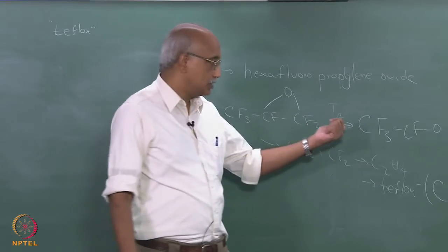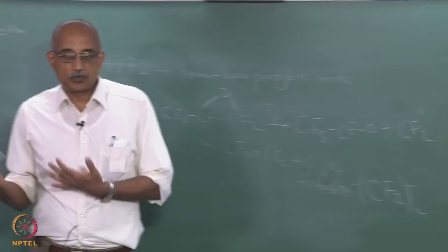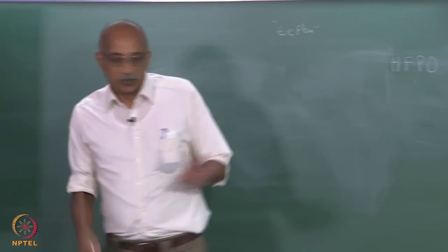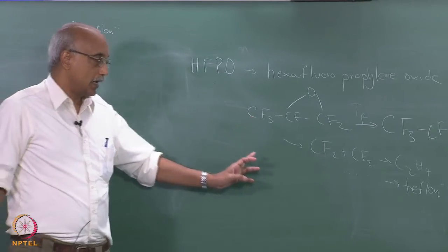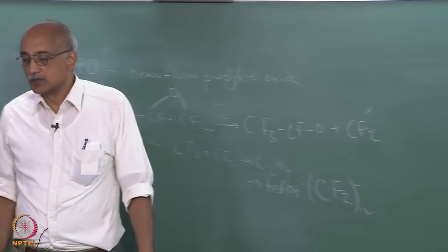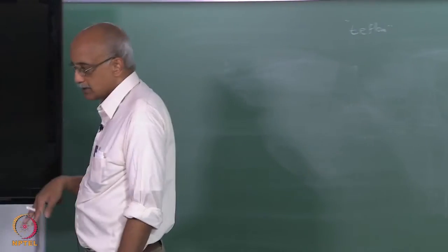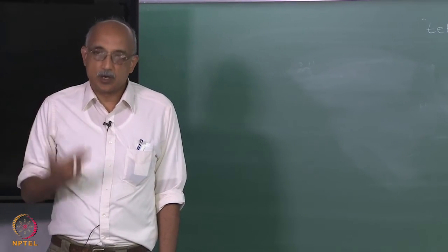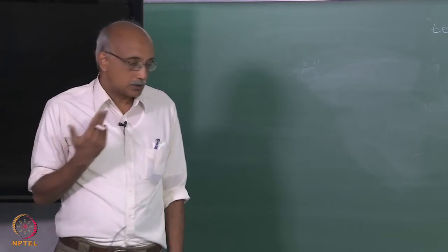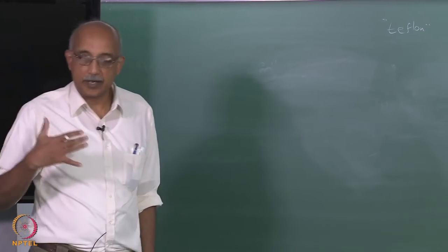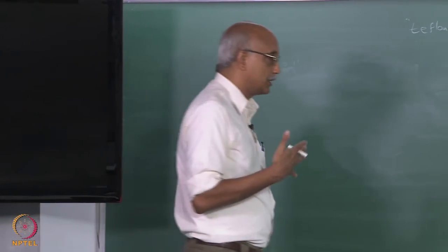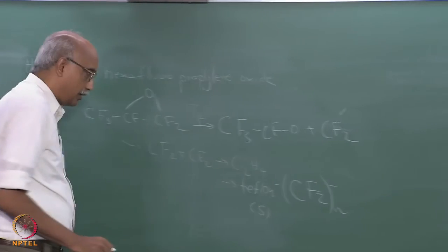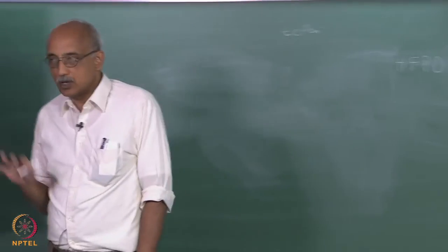And so in a system where, for example, let's say that you're just using a heat source to do this initial dissociation, how do you go from that to form a Teflon film? You really cannot. Now, the advantage of doing this in a CVD reactor is between the time that this dissociation happens and the time that you have to form this molecule, you are providing sufficient residence time as well as a flow path inside the reactor where these association reactions can continue and you can keep forming higher order molecules to the point where at the substrate, where now you have a heterogeneous equilibrium, it becomes thermodynamically favorable to form Teflon solid. So the solid Teflon coating only forms at the substrate